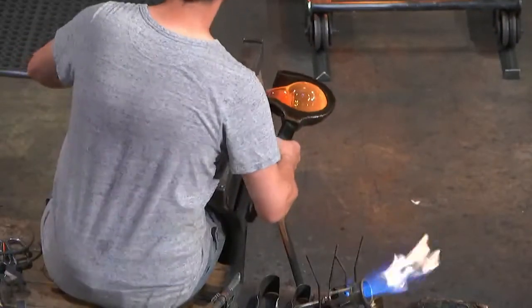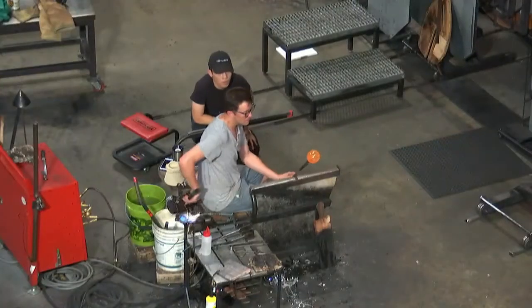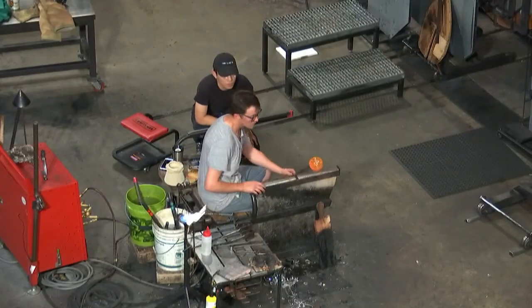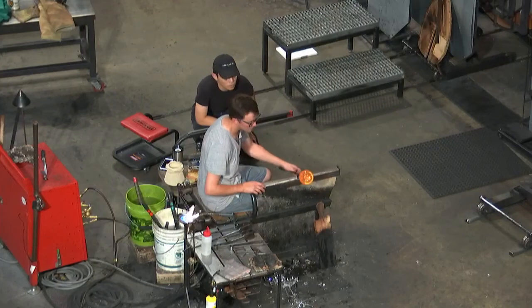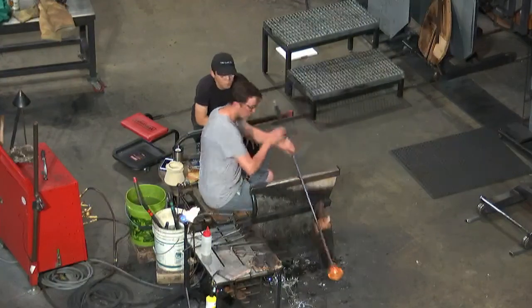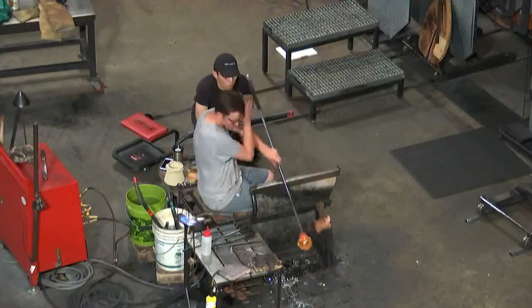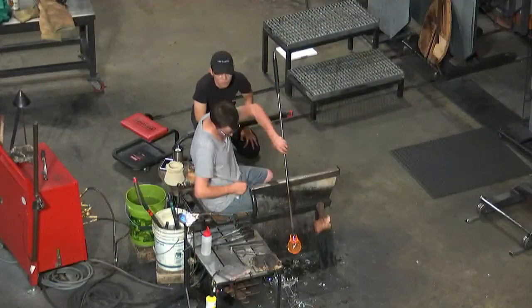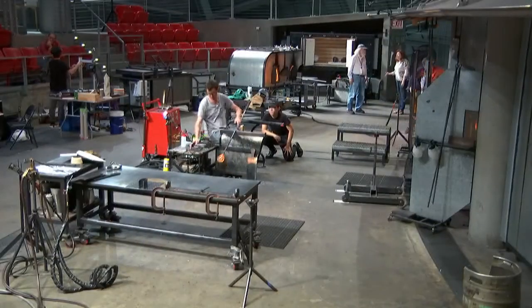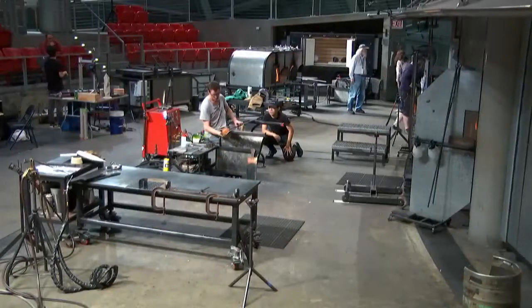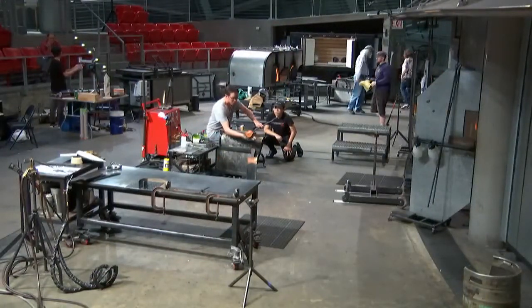It's heated right now at 920 degrees. It's on a computer cycle. For 6 hours, it will slowly make its way from 920 to 600 degrees. When it hits 600 degrees, it will cool down back to room temperature quite fast. The majority of the cycle is spent from 600 to 900. Yeah, any question? Anytime, anytime.